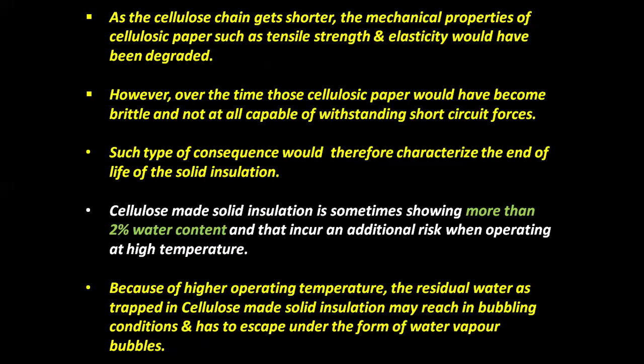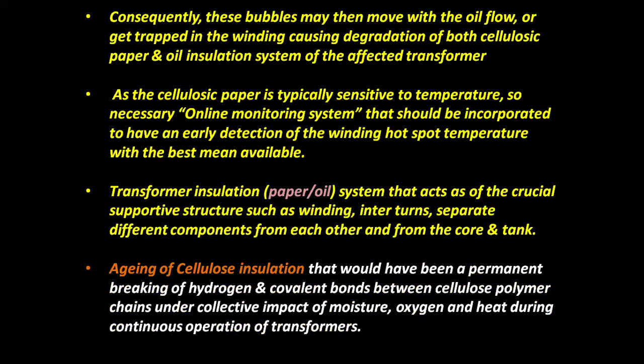Cellulose made solid insulation sometimes shows more than 2% water content, and that incurs an additional risk when operating at high temperature. Because of higher operating temperature, the residual water trapped in cellulose solid insulation may reach bubbling conditions and escape in the form of water vapor bubbles. Consequently, these bubbles may move with the oil flow or get trapped in the winding, causing degradation of both cellulosic paper and oil insulation system of the affected transformer, as the cellulosic paper is typically sensitive to temperature. So, a necessary online monitoring system should be incorporated to have an early detection of the winding hotspot temperature with the best means available.